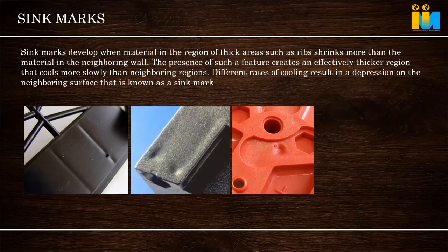Second is, we have maintained that the rib thickness is properly maintained as per product design. Still sink comes, because why? Because our gate is already frozen. It could be due to the feed system also. We are giving pressure in the machine, but it is not going to the cavity. We are giving adequate holding time, it's not going to the cavity. So the cavity will not get packed properly during the packing time. So what happens? It will show as a sink. So increase the gate size, proper feed system as per our MPA. We have to ensure no pressure drop in the feed system.